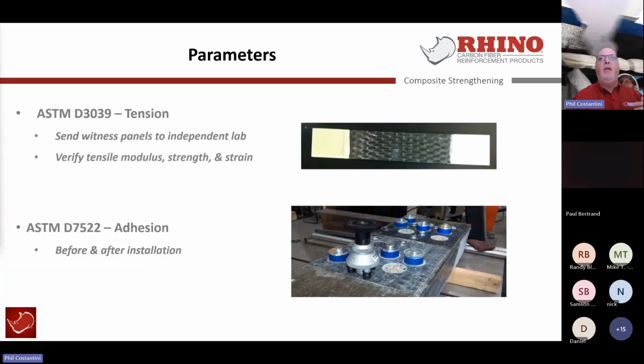So for tension tests, we take samples of our material. We do this on a regular basis. This is to ensure our quality control from an internal perspective of the tension tests we do, so we achieve the proper tensile modulus and strength, and that goes back to what we talked about again, stress over strain.